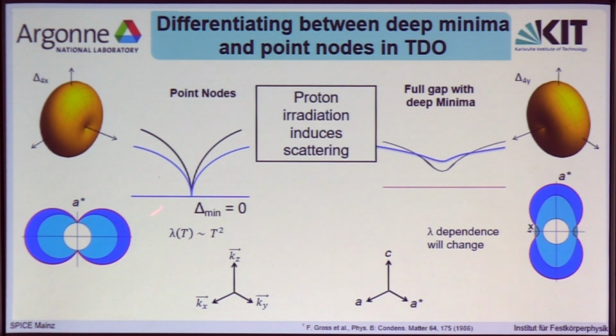Proton irradiation induces scattering in the samples, and it will weaken the superconductivity and reduce the superconducting gap amplitude. However, it would do that differently for different gap structures. For the point node system with symmetry-protected point nodes, these nodes of course have to stay. So we will only reduce the amplitude, but not change the structure, so we will still expect to see T-squared dependence. However, for the minimum case, which is not symmetry-protected, this additional scattering will wash out the superconducting gap structure, and while we reduce the overall amplitude of the gap, we will lift the minimum, and might thus see a change in the low temperature dependence of the penetration depths.